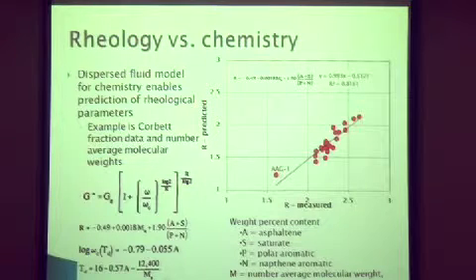And this shows some old data going back to 1992. This is a paper a colleague of mine, Dave Anderson, published, and it shows how the R value here, this is what was measured, rheometer, what's calculated, chemistry. Here's a few equations: asphaltene, saturate, polar aromatic, naphthene aromatic fractions within a bitumen, and the molecular weight of that sample.